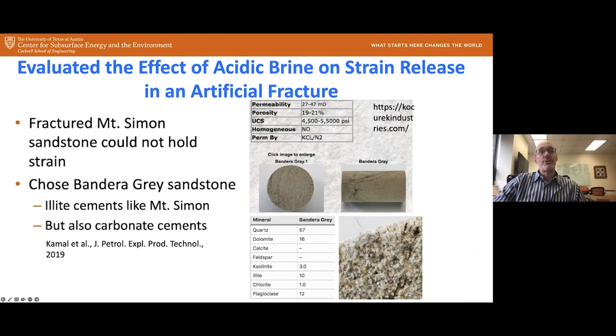So what we chose then is to use a Bandera gray sandstone. Like the Mount Simon sandstone, it's mainly cemented by illite clays. The Bandera gray also has illite cements, but it also has carbonate cements. And so if we look here at the Bandera gray, it's primarily quartz. It has about 16% dolomite, 10% illite, and 12% plagioclase, and then minor amounts of kaolinite clays and chlorite. You can also see there's some banding within it. And when you get down at the microscopic scale or the millimeter scale, you start to see it's quite heterogeneous with lots of distributions of minerals.